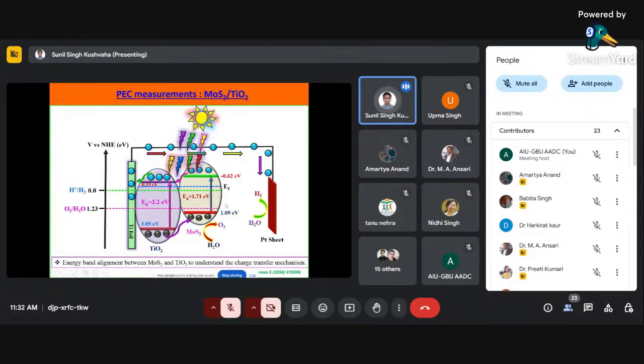As I mentioned, this band edge position can also be calculated using XPS, that is X-ray photoelectron spectroscopy. Another technique is UPS, that is ultraviolet photoelectron spectroscopy. From there we can get the work function, and from XPS some calculation is there. We can get the conduction band edge position and valence band edge position, and the band gap we can know from our photoluminescence spectroscopy and this UV visible measurement. So that is the two or three techniques to get this. What is the band gap? What is the conduction band position? What is the valence band position? And then we propose different kinds of band diagrams to support the findings.